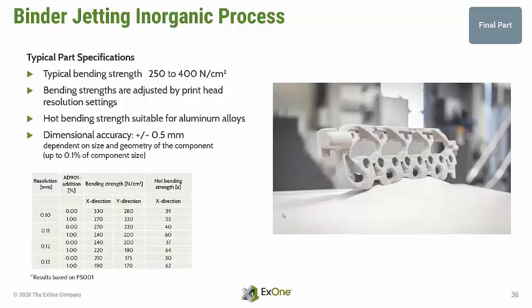Even though it is challenging for a process with heat treatment for curing, the dimensional accuracy of the part is at plus minus 0.5 mm, dependent on size and geometry of the components. However, we have successfully demonstrated with our customers that these tolerances can get significantly improved in volume production.